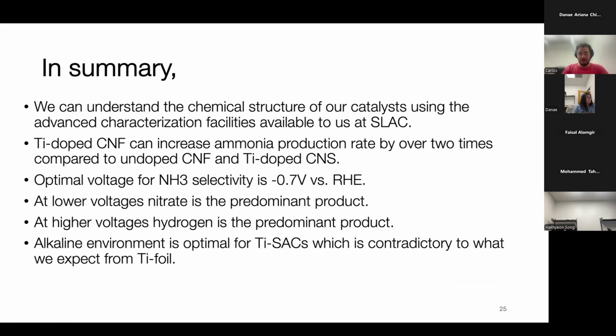And finally, we started this project to see if we could make a catalyst that would work well in an alkaline environment that was titanium based. This was contradictory to what we usually see with titanium foil, which is usually in very acidic conditions, but we get a couple of benefits from operating in alkaline environments because any ammonia that we produce is going to be in the gaseous state. So it's then very easy to concentrate and purify because you can just have an acid trap that captures that ammonia into ammonium.